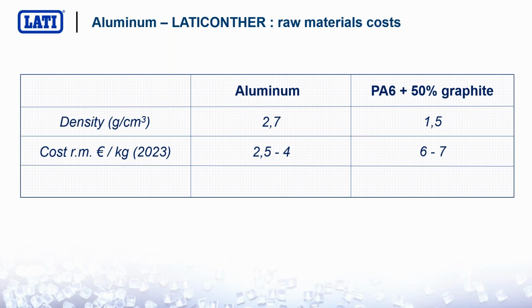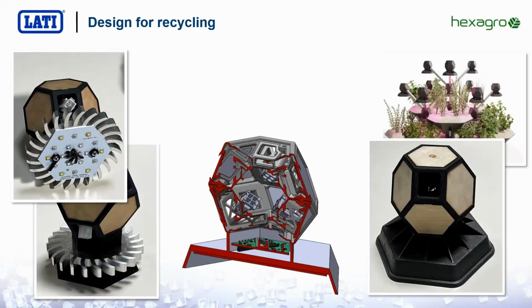So if you do the math, you multiply by density, you see that the cost of the raw material per cubic decimeter, that's actually the cost per volume, is competitive. So not only from a performance point of view, but also from a GWP point of view and from a cost point of view, thermally conductive plastics can be a winning choice. And it would be even better if we were able to properly recycle them.